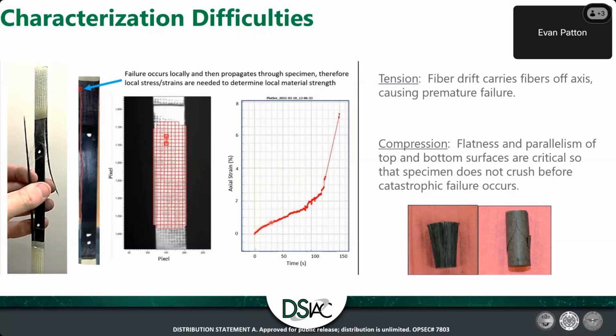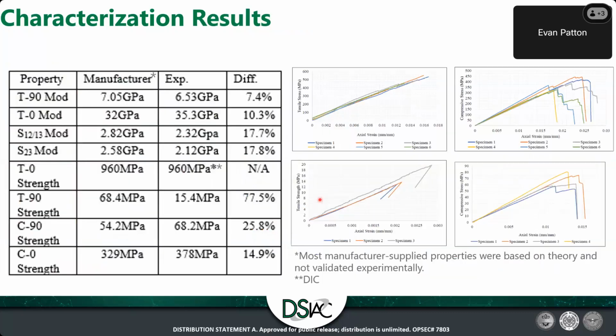And what we saw was that we had a pretty linear response, which we expected, and then all of a sudden a failure. And we were able to obtain a failure strain and then back calculate it with the linear elastic moduluses, as we saw in this graph here on the top left. We were able to obtain a localized theoretical stress limit. And I threw some more graphs up here. This top one is the 0 direction. Bottom is the 90-degree direction, which you're pulling, I guess, the fibers apart from each other. And then the right-hand side are both the 0 and 90-degree compression tests.